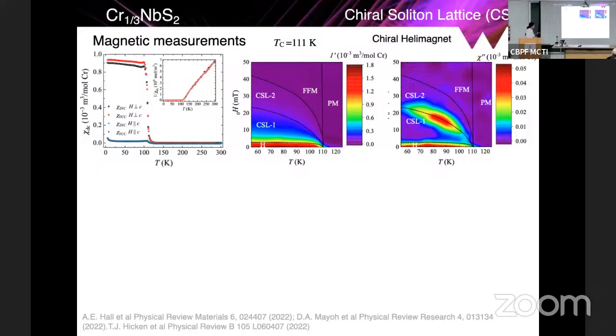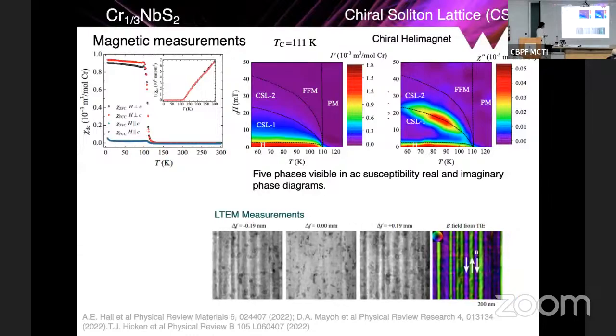So we were able to clearly identify this as the helical state, the ground state. And then it goes to a state which is highly helical. And then it goes to another state which is highly ferromagnetic. And then it goes to the fully forced ferromagnetic state. Okay. So this is the imaginary part, and this is the real part of the susceptibility.